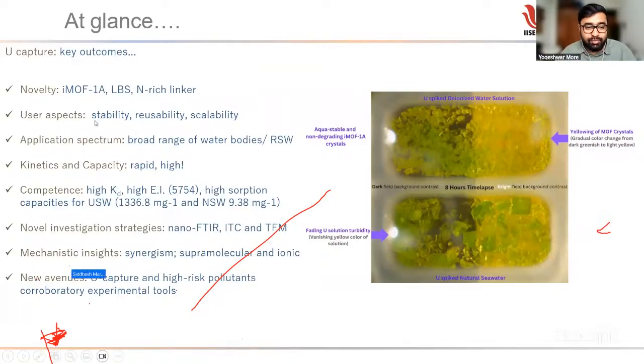Then the kinetics and capacity. Its capacity is high, and kinetics is moderately fast. And the competence: how is its competence decided? Competence is decided by the enrichment index, and we have one of the highest enrichment indices, that is 5754, as decided by the global standards, and a high adsorption capacity for uranium-spiked water, that is 1336.8, as well as 9.38 per milligram.